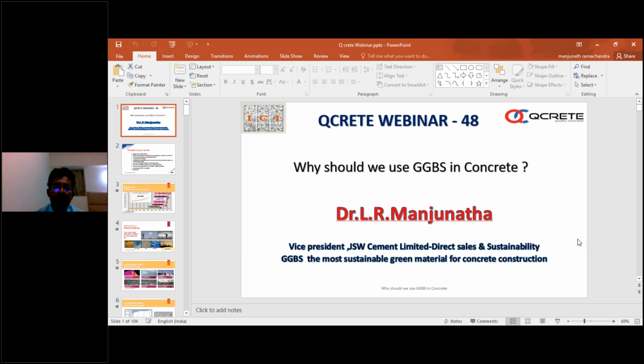The next question is asked by Mr. Shivashankar TV: why is PSC not getting strength in higher grades of M50 and above? It depends on what percentage of GGBS is being used in the PSC cement. To get strength, you have to increase the cement content. Higher grade of concrete requires a higher clinker factor also. For higher grades of concrete we try to use about 35 to 40% maximum. As an example, in L&T Carwar seabird, they are using 70%. They are getting whatever strength is required, even with 60 to 70% of GGBS.